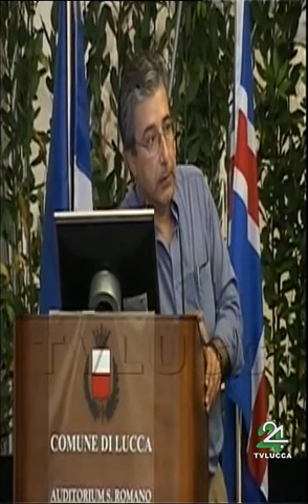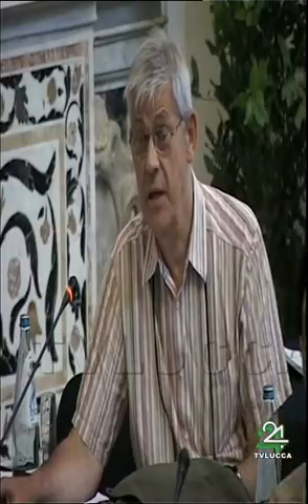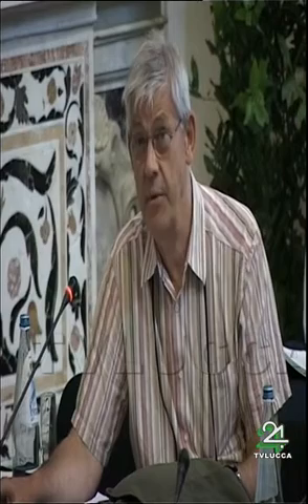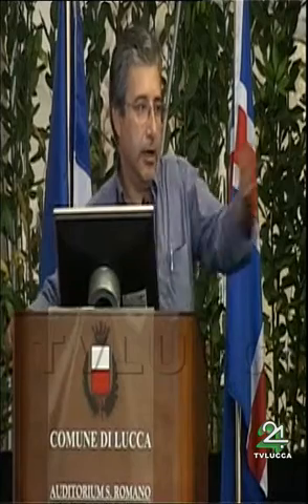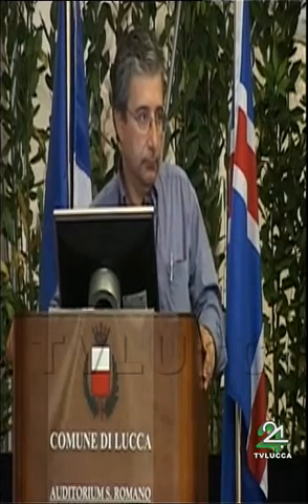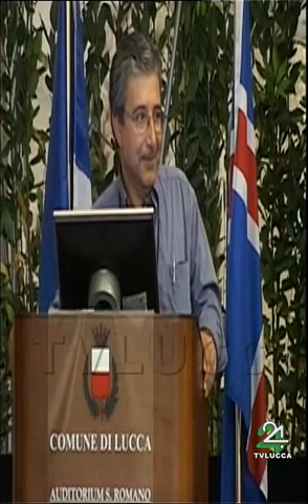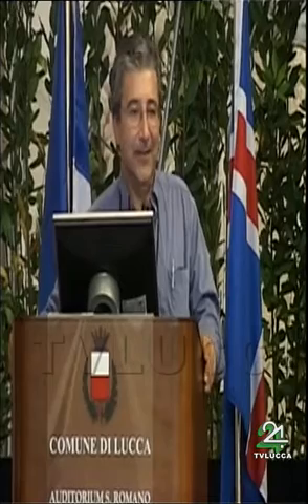We are very interested in samples which are showing, of course, greater heat of adsorption, because that's where we understand the mechanisms. At this stage, it doesn't terribly matter whether they have very large surface areas, because if you understand what you're doing, then you can begin to design something with a bigger surface area. Okay, so you're looking for any sample, any interaction, anything with a stronger interaction than the 3 kilojoules.